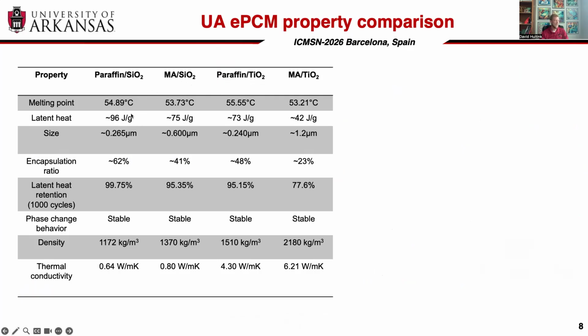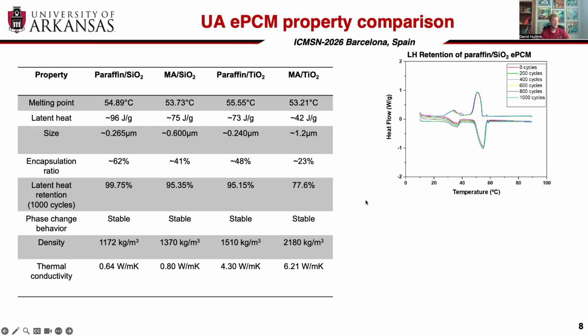And the cool thing here is that we are able to achieve latent heat capacity within these ePCMs that is still meaningful. But again, with the shell, we have an area of that particle that is now non-thermally active. So that's what we refer to as encapsulation ratio, because essentially 62% of the mass of that particle is participating in latent heat exchange is what this refers to. And we also see some good things about latent heat retention over a long period of cycling.